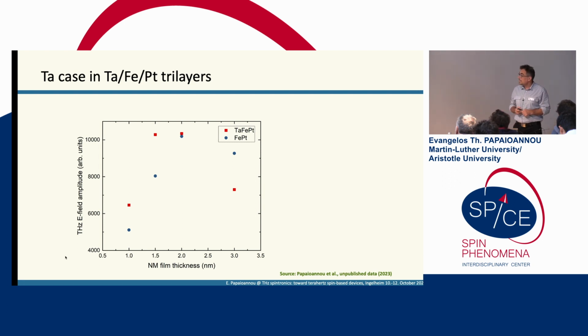So the tri-layer is higher than the bilayer, as to be expected, as is the case for the tantalum iron platinum, for example, or the tungsten iron cobalt boron platinum, but not for the thicknesses that we were expecting.